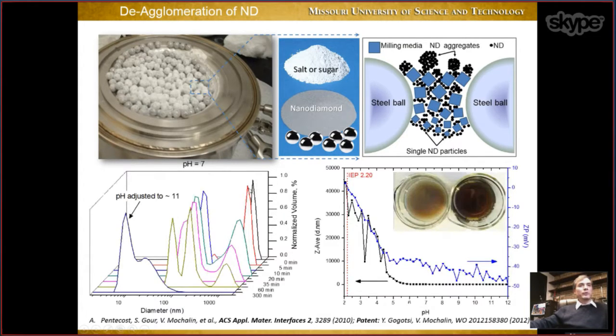And to demonstrate how they work, I show here, first of all, milling kinetics. So we mill nanodiamond with salt in this case for different amounts of time, shown here. You can see that we start with nanodiamond which are heavily agglomerated. The size of agglomerates is more than 1 micron, this black curve here. Over the milling time, over 5 hours, you can see how this peak goes down and the amount of small particles increases. And eventually, with pH adjustment, we can reach almost primary particles.